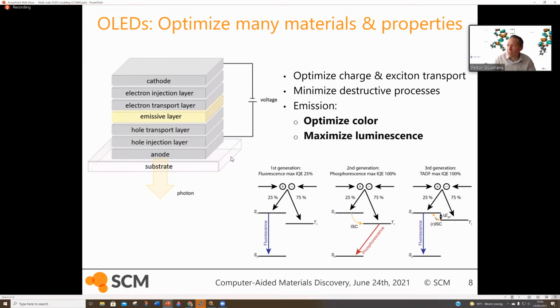A lot of people have been using ADF to optimize these types of processes, but ideally you want to optimize the entire OLED stack simultaneously. So that is something that we're currently working towards. But first, have a look at the emission properties. And so in 2005, Tom Ziegler, who I mentioned in the beginning, together with a few collaborators, implemented in our molecular DFT code time-dependent density functional theory, with which you can calculate excited state properties in combination with spin-orbit coupling.